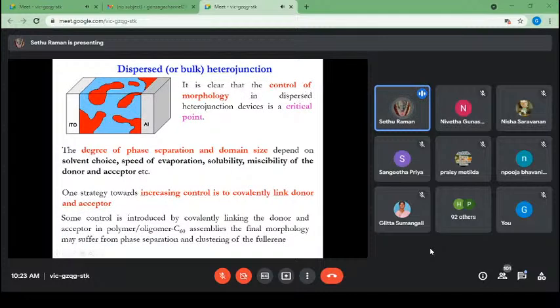It is clear that control of morphology in dispersed heterojunction devices is a critical point. The degree of phase segregation, phase separation, and domain size depends on the solvent, speed of evaporation, and solubility of the donor and acceptor. We prepare a blend, and then the blend is deposited between ITO and aluminum. That blend makes some domains and phase separation. Each domain boundary acts as a dissociation site for the excitons. So we can dissociate the exciton in an efficient way by using the bulk heterojunction concept.